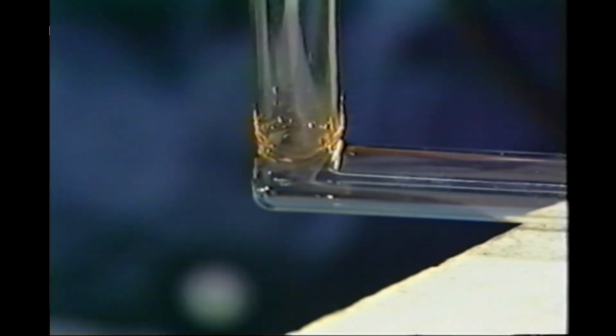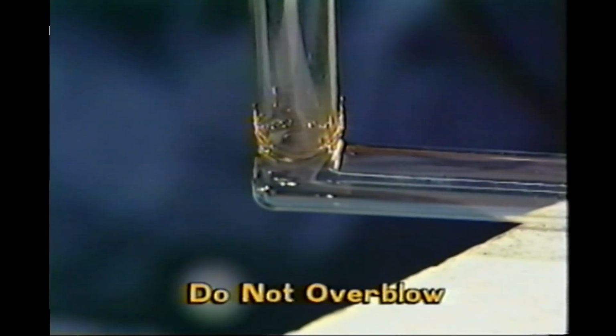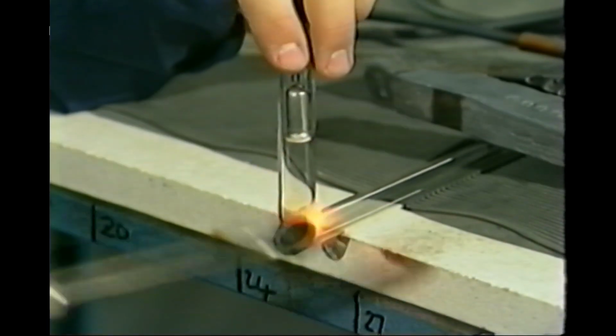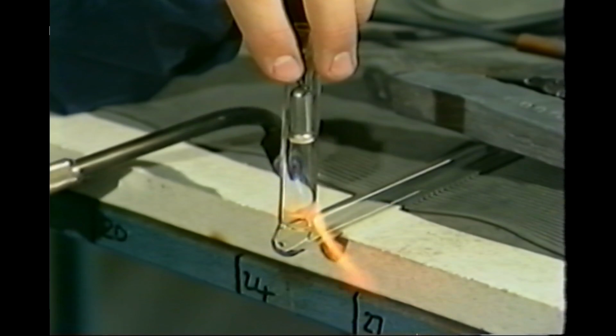During melting, the diameter of the electrode glass will reduce. Blow gently until the correct diameter is restored. Do not overblow, as this will thin the electrode tube wall thickness. Heat up the glass again and repeat the melt and blow.